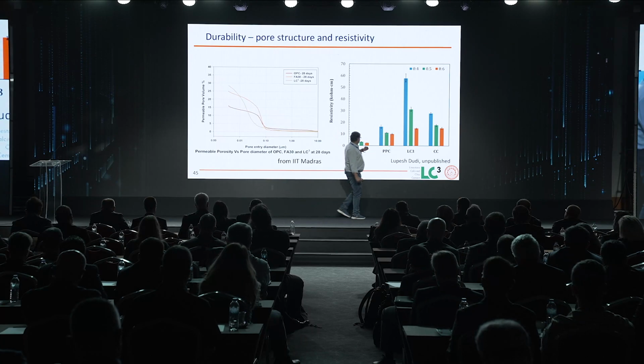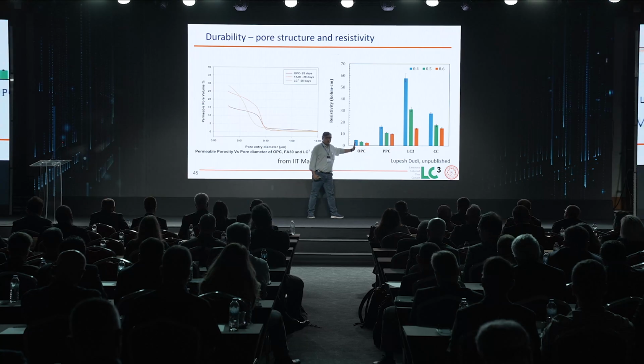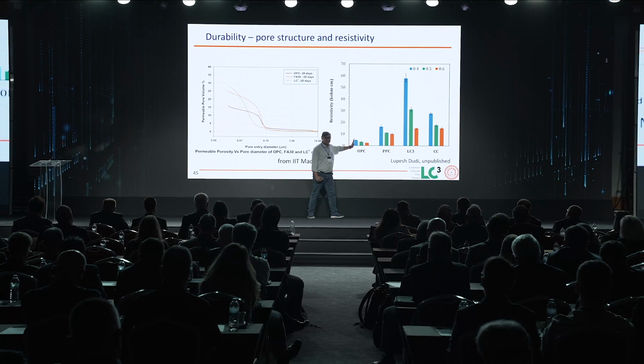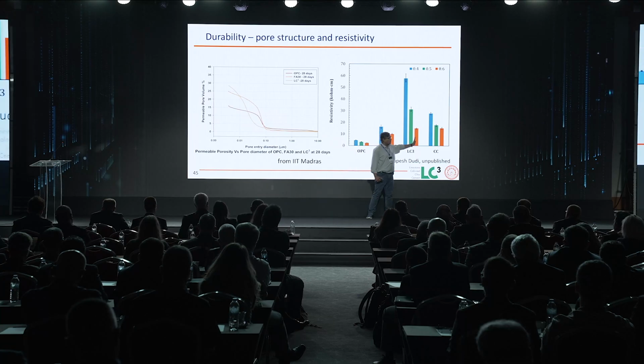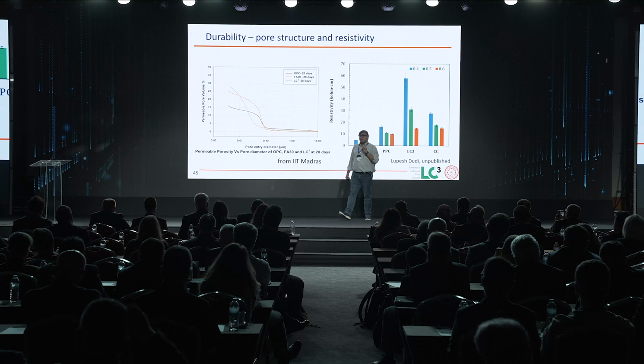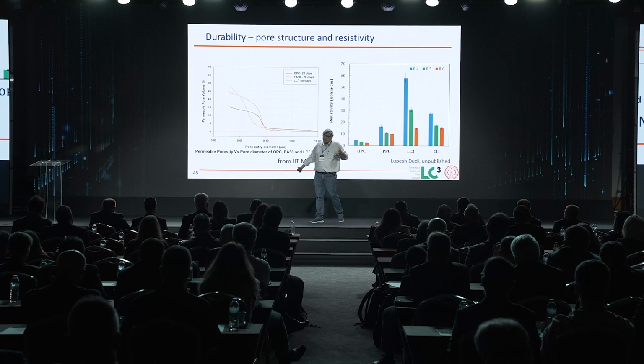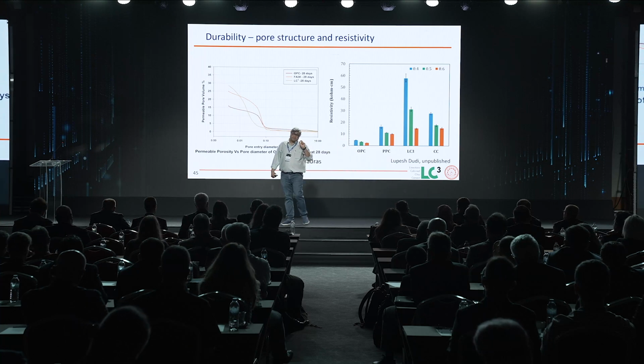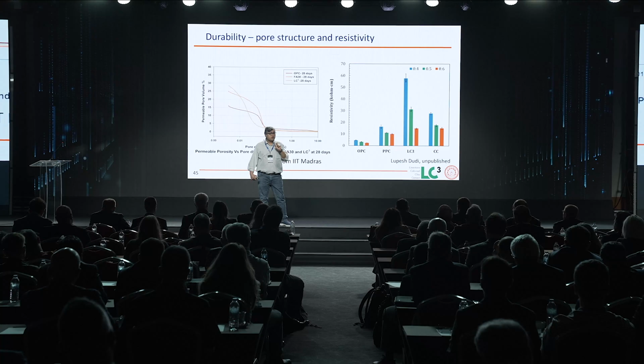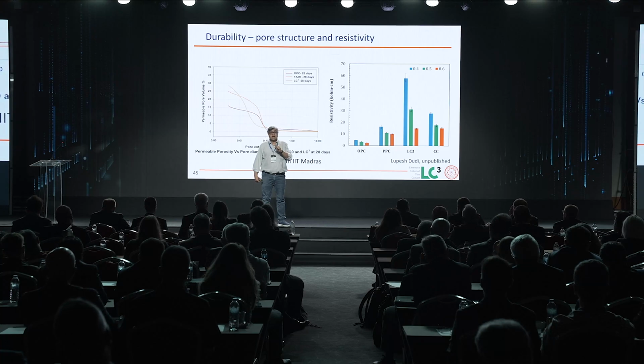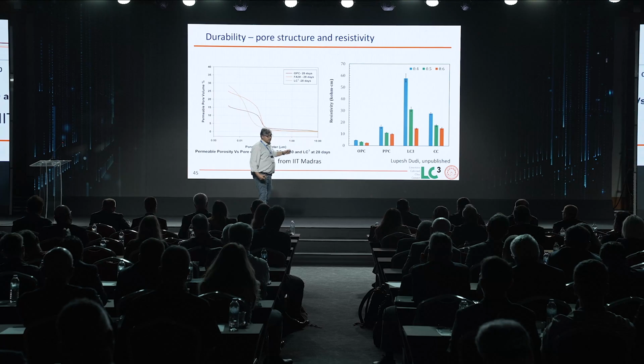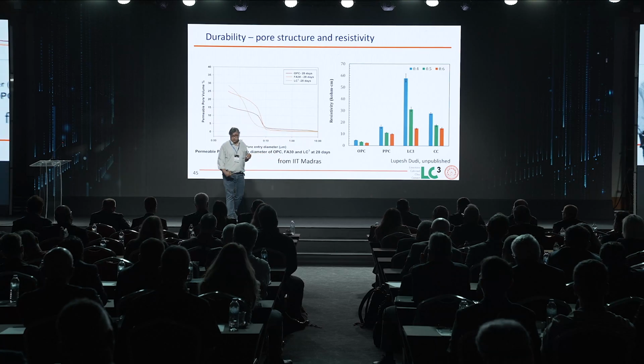So you can see here that an OPC concrete made with 0.4 water to binder ratio has a lower resistivity than an LC3 with 0.6 water binder ratio. So for applications where durability was your concern, for example, chloride ingress was your concern, and that was the only reason you were going with a low water binder ratio, you can now live with a higher water binder ratio because the chloride ingress is much slower in these cases.